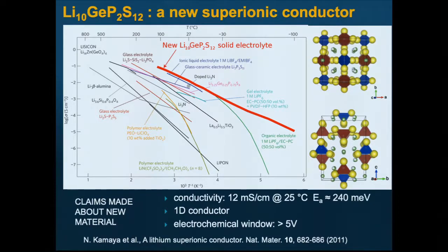Well, in 2011, there was an interesting paper in Nature Materials by Kamaya et al. who showed a new conductor, lithium germanium thiophosphate, LGPS as it's called now, which on an Arrhenius plot has the same conductivity at room temperature as liquid electrolytes. Interestingly, it actually has a lower activation energy than liquid electrolytes, meaning at low temperatures it's even better than the liquid electrolytes.